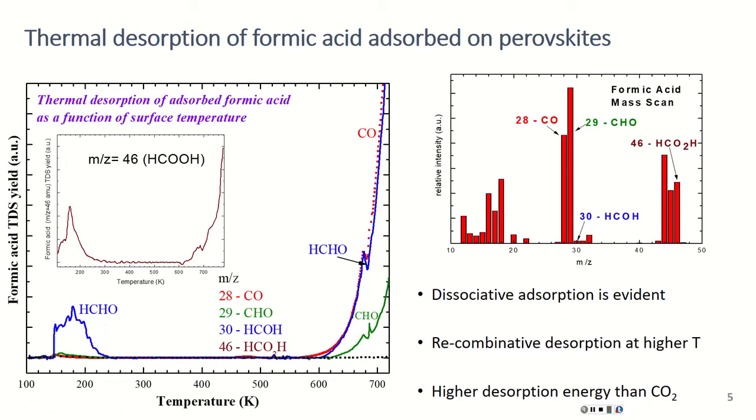I guess the question is, what is the dynamics actually of the process? Does it dissociate on impact or is it thermally activated? I don't think we can really say that. We can have both, on impact. So you're saying that it may dissociate right when you deposit. It looks like it dissociates at low temperature, and then the fragments are bound on the surface with a relatively large binding energy. And what you then see desorbing are the fragments, right?